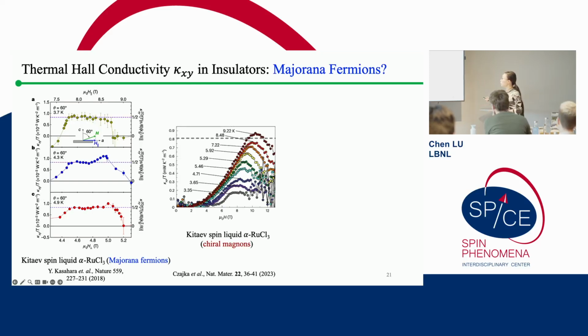However, later on, other groups tried to repeat this result, but they saw something slightly different. The figure in the middle is the result from Professor Ong's group in Princeton. They also tried to measure the thermal Hall effect in alpha ruthenium trichloride. They saw a non-zero thermal Hall effect, but no obvious half quantization in this signal. Their theoretical explanation is not based on Majorana fermions, but instead on chiral magnons or topological magnons, especially tied to the Kitaev-Heisenberg model.